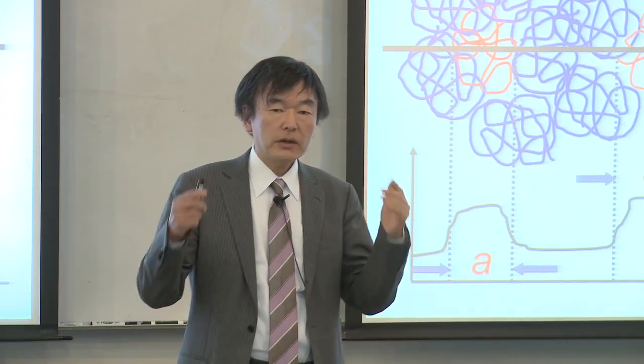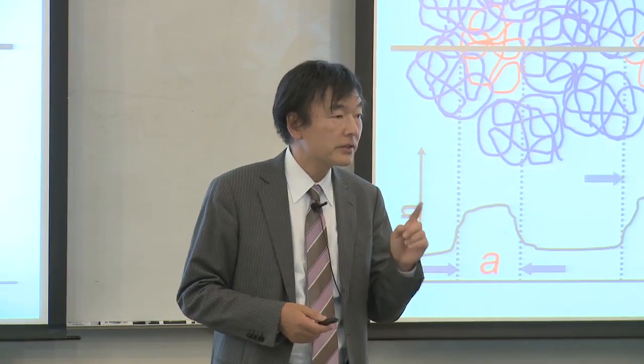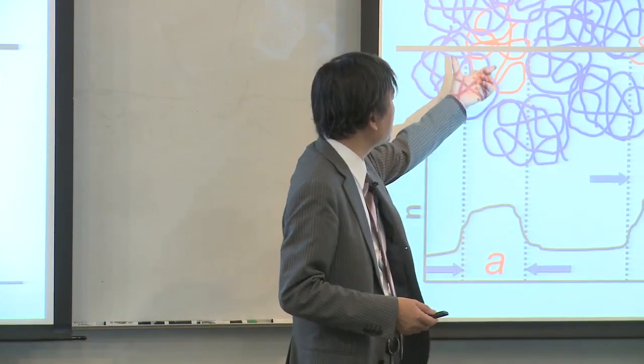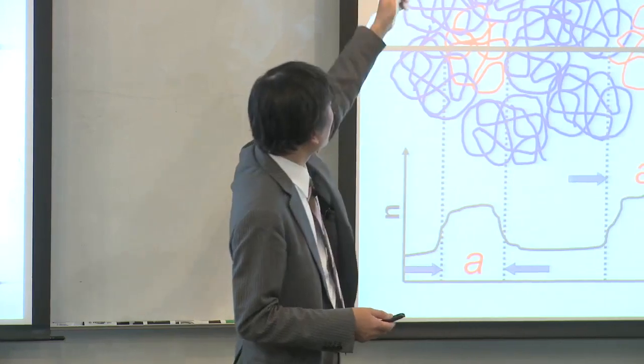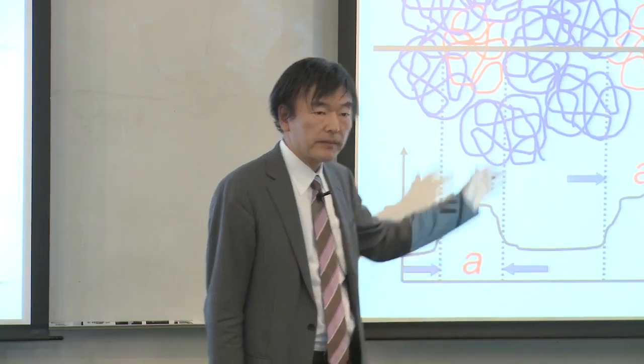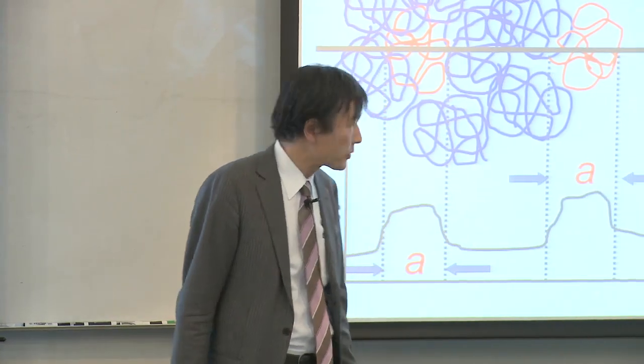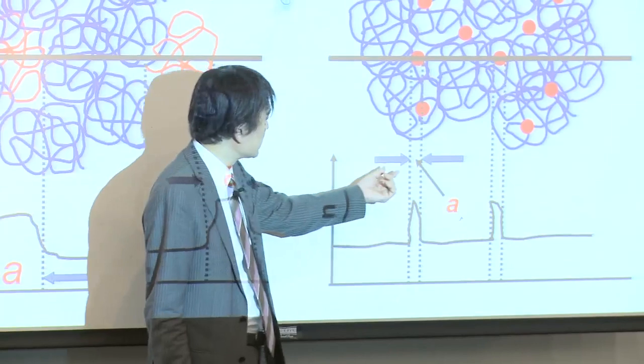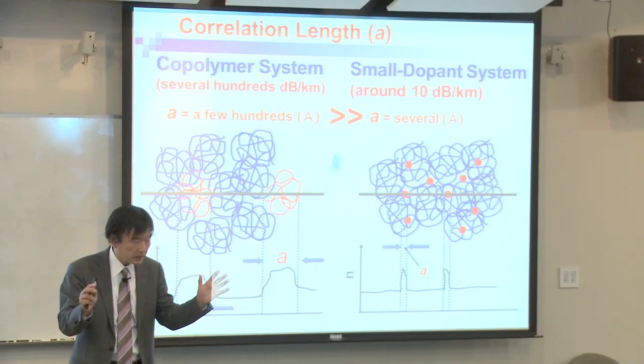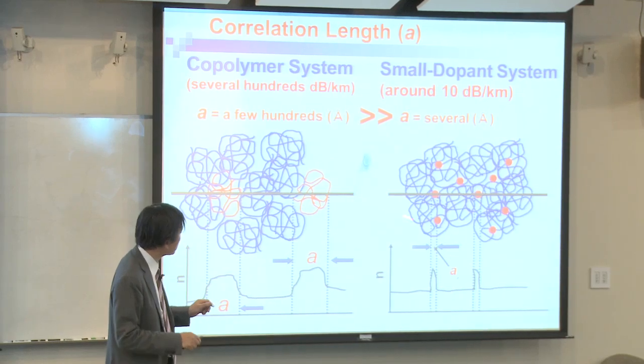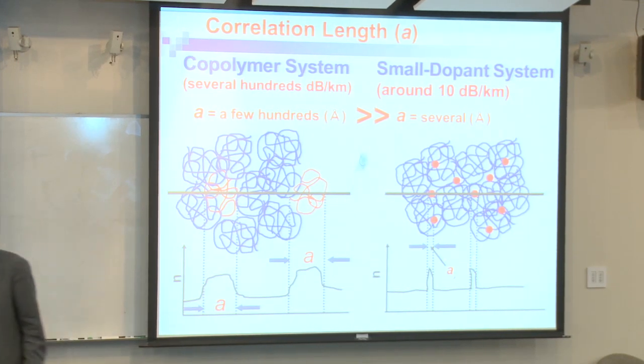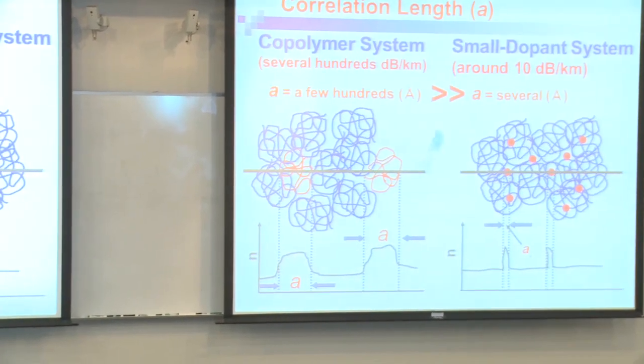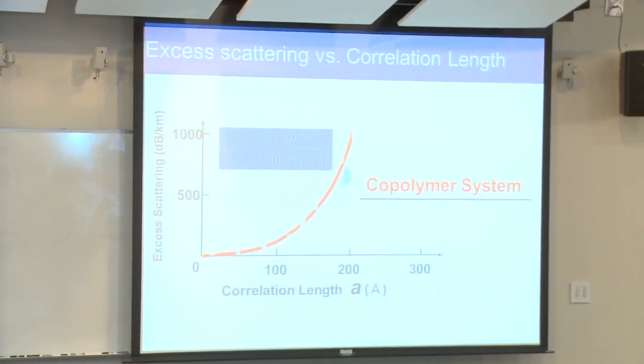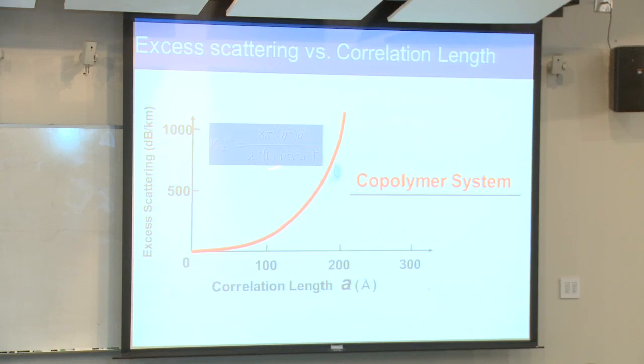So, if I continue the copolymerization process, this is the inherent scattering loss coming from the minimum size of the polymer coil. That is still a few hundred angstroms. Then, I stopped the copolymerization process, and I introduced adding small dopants. A small dopant has a size of several angstroms. So if the small dopants are not aggregated, the minimum size is very small compared to a copolymer. Then this several angstrom is inserted into the equation.